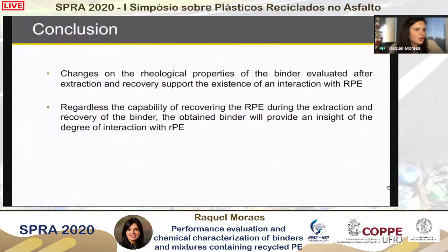Therefore, we can conclude that the change in the rheological properties of the binder evaluated after extraction and recovery support the existence of an interaction between the recycled plastic and the base binder, even though the incorporation of the plastic was through the dry process. And regardless of the capability of recovering this recycled plastic during the extraction and recovery of the binder, the obtained binder will always provide an insight of the degree of interaction with the recycled plastic.